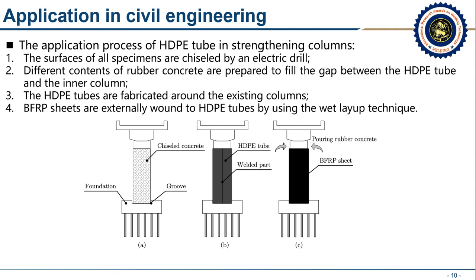The application process is: first, the surface of all specimens were roughened by an electric drill. The second, different contents of rubber concrete were prepared to fill the gap between the HDPE tube and the inner column. Third, the HDPE tubes are fabricated around the existing column. Fourth, BFRP sheets were externally wound to HDPE tubes by using the wet layup technique.